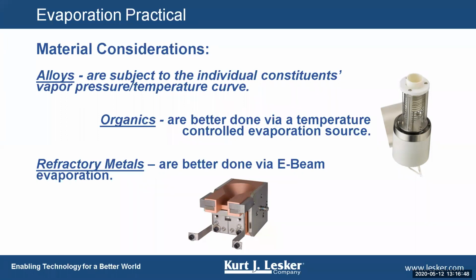Yeah, for insulating materials, I don't want the beam to focus, in essence. If you can envision an irregular shaped piece of silicon dioxide, maybe 2 millimeters in diameter on average, with all sorts of jagged edges, the thermal conductivity between it and the piece underneath is quite low. So if I were to focus the energy of the beam down to 2 millimeters,